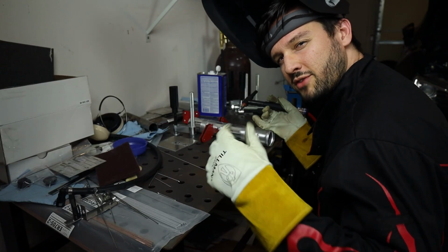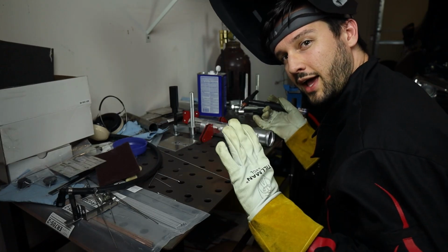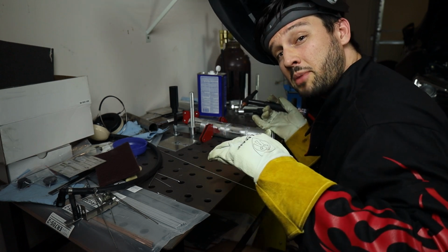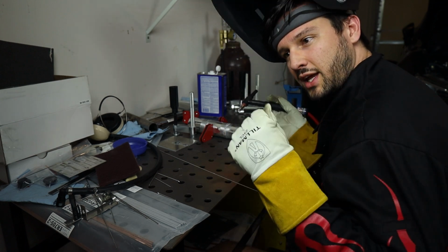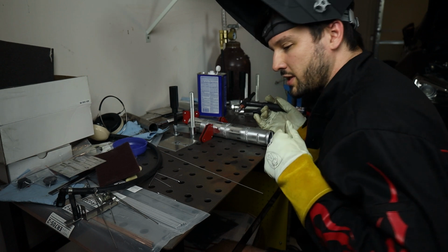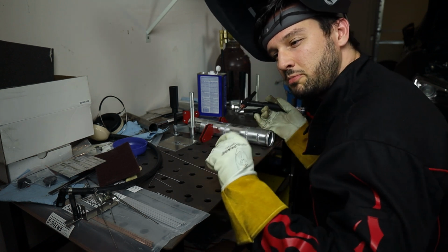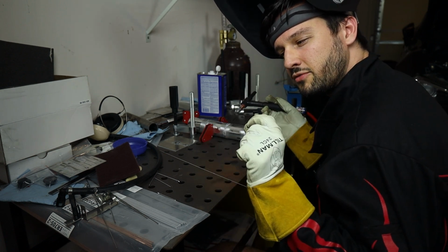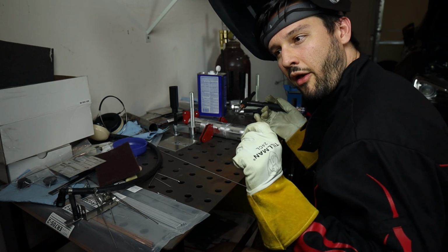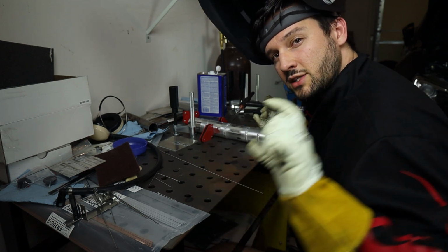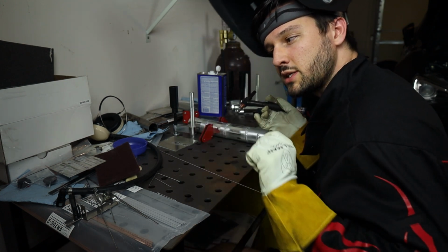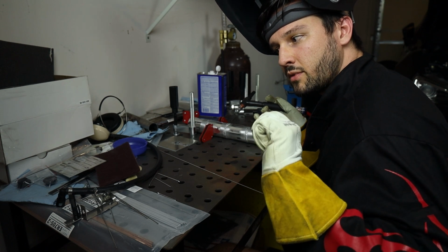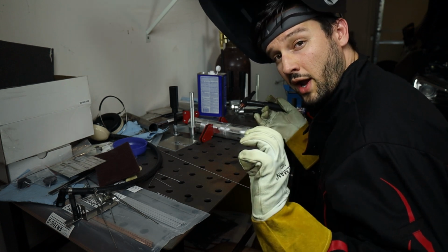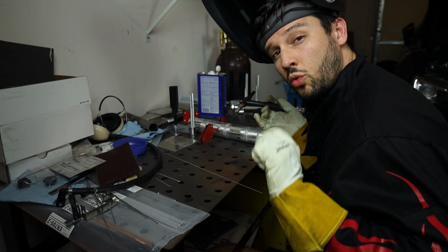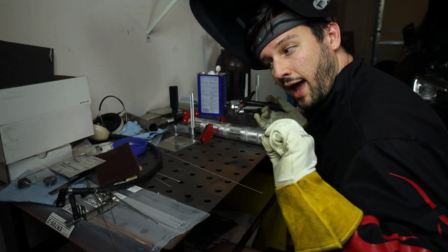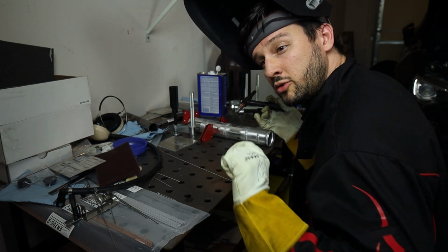Little bit of trouble getting that first pull started. I was a little slow ramping up my amps. I needed to get that up faster, get that weld pool and get moving. I noticed that as I was advancing my weld pool, it almost looked like a hole or a crater in the two unjoined pieces was forming as I was approaching it with the weld pool.